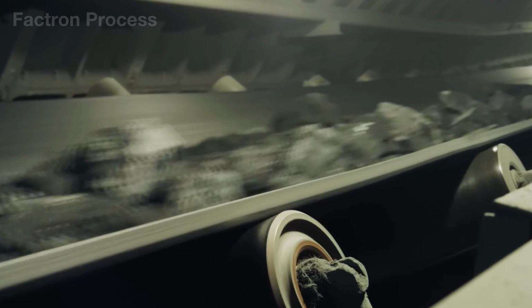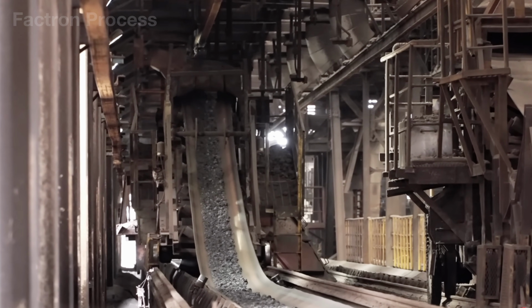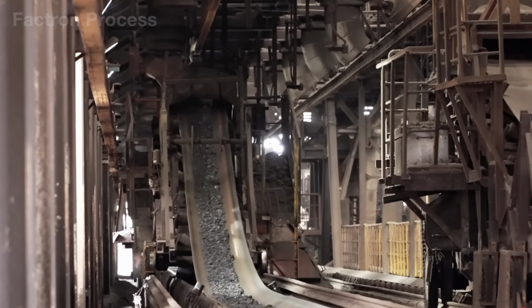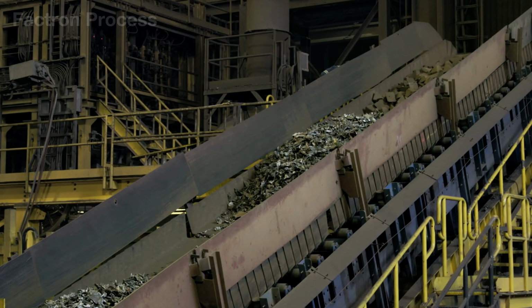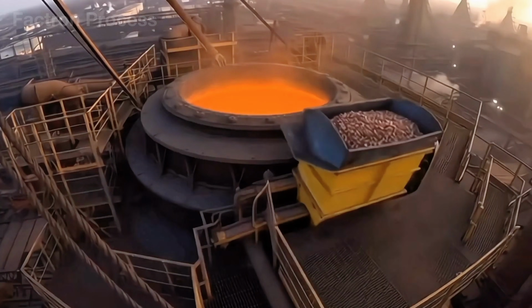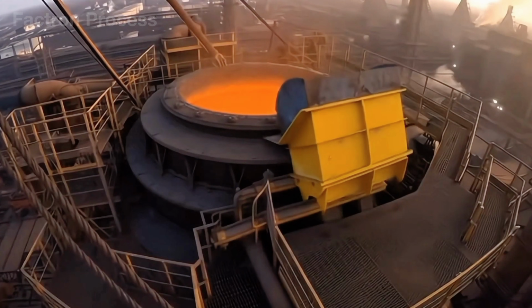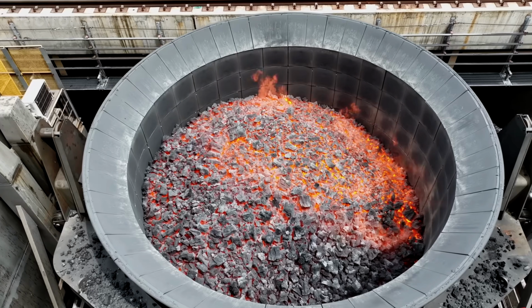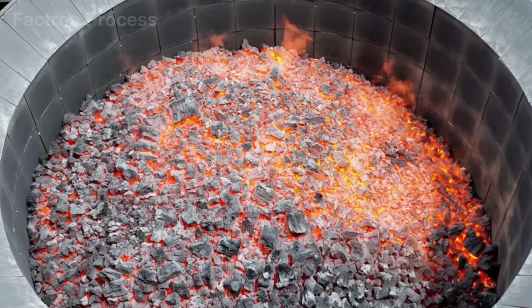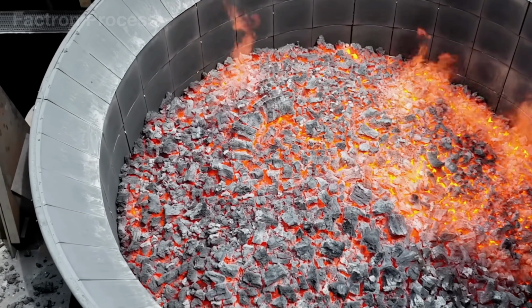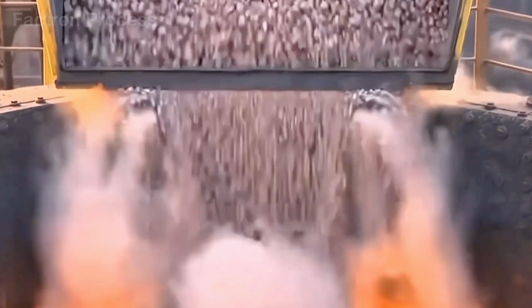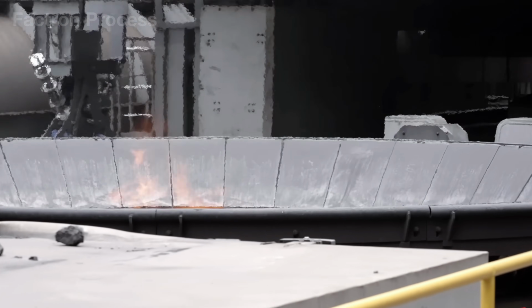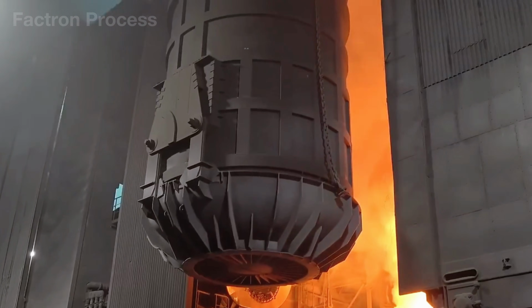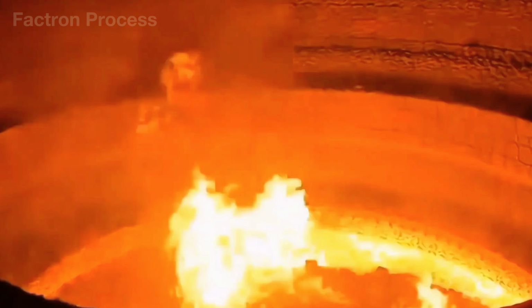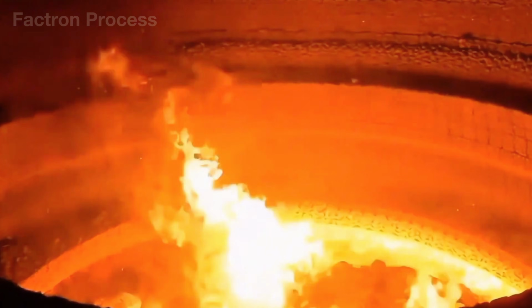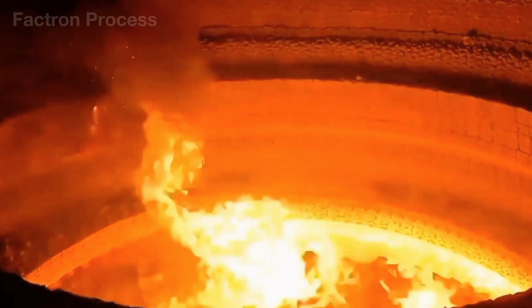The journey now enters its most critical stage, steelmaking inside a massive electric arc furnace, or EAF. The process begins as scrap steel is dumped onto the furnace bottom to form a load-bearing base. Sponge iron, or DRI, together with quicklime and carbon, is then continuously fed through an enclosed conveyor directly into the center of the furnace. 3 graphite electrodes descend and release an intense current of 80,000 amps, generating a plasma arc with a core temperature above 10,800 degrees Fahrenheit, and melting the metal into a liquid bath, heated beyond 2,900 degrees Fahrenheit.